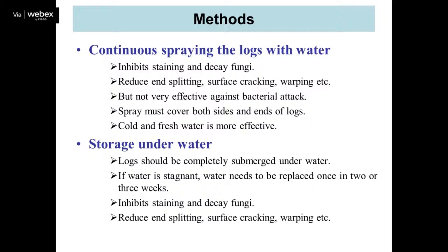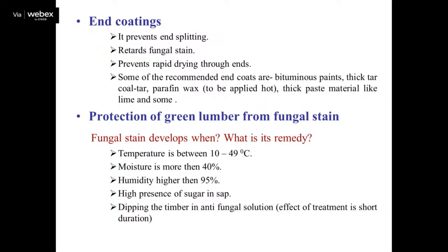Therefore, most of the soluble sugars, which attract the insects, get drained out. Further, because of these water saturated conditions, the growth of fungal decay organisms and insect attack were also prevented. As the logs are in the saturated condition, end splitting, surface cracking and other defects arising in the logs were prevented. End coating, as I told, prevents end splitting.